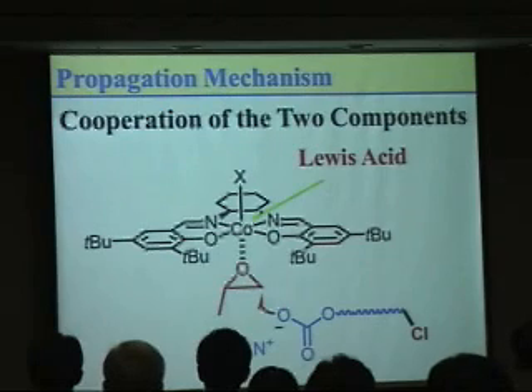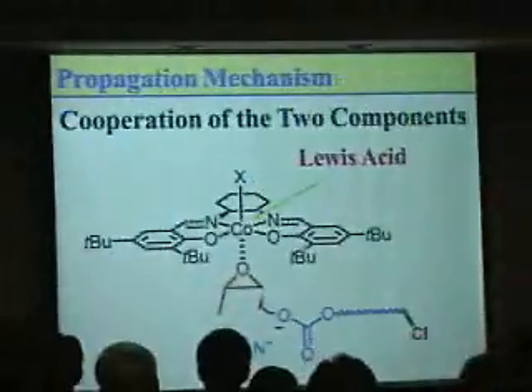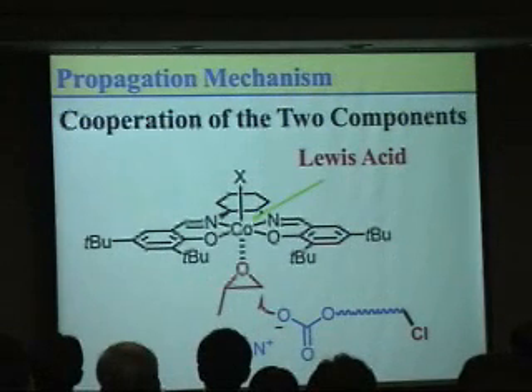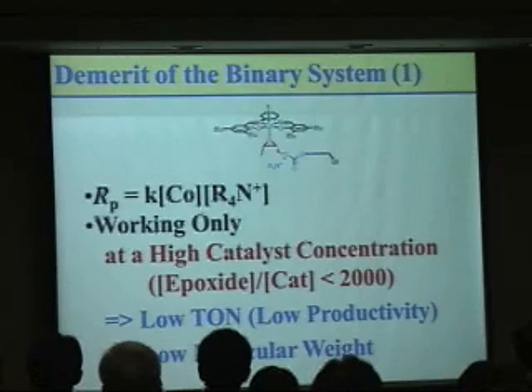So the plausible propagation mechanism is like this. The cobalt center acts as a Lewis acid activating the coordinated epoxide, while the carbonate anion, which is derived from the anion of the quaternary ammonium, attacks the activated epoxide. And under this propagation mechanism, we have some problems. So the rate of polymerization should be second order kinetics. So under this situation, it works only at a high catalyst loading.